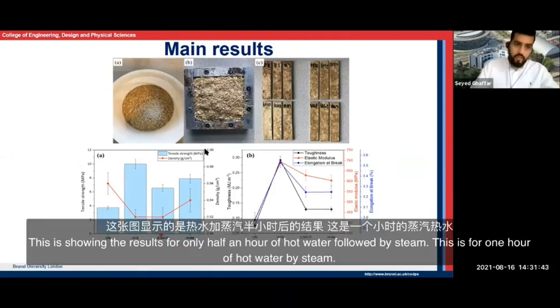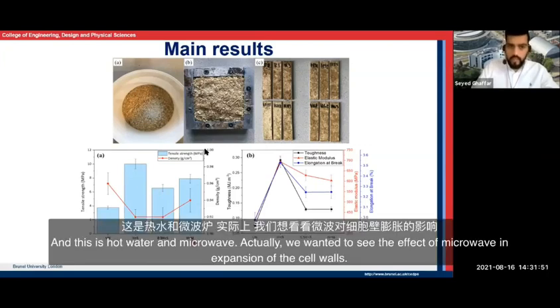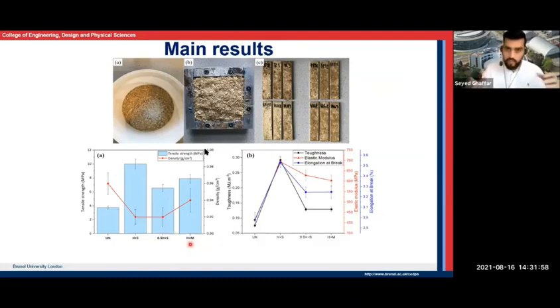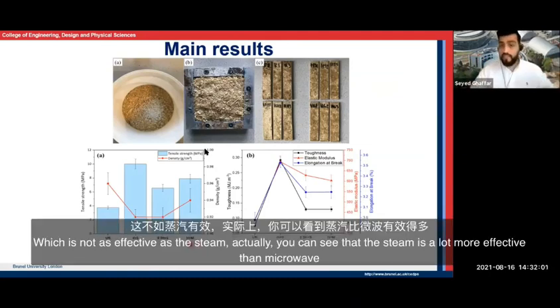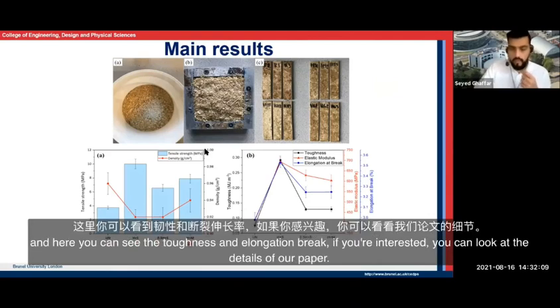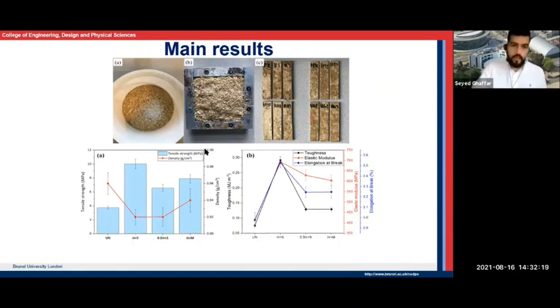This is showing the results for only half an hour of hot water followed by steam. This is for 1 hour of hot water by steam. And this is hot water and microwave. Actually, we wanted to see the effect of microwave in expansion of the cell walls, which is not as effective as the steam. You can see that the steam is a lot more effective than microwave. And here you can see the toughness and elongation at break. If you're interested, you can look at the details of our paper.